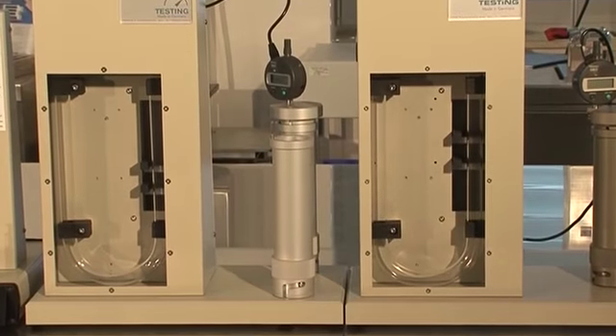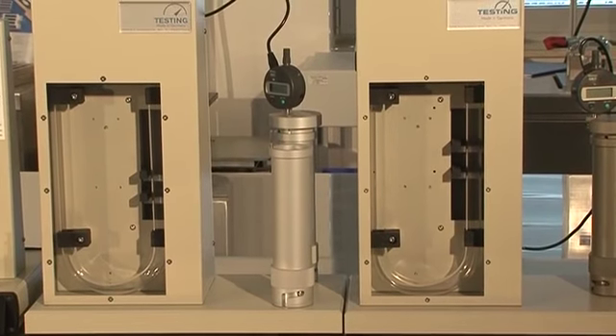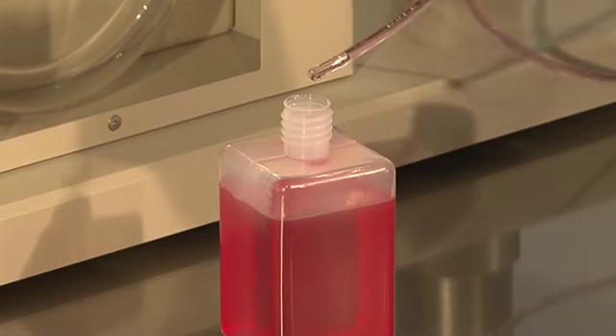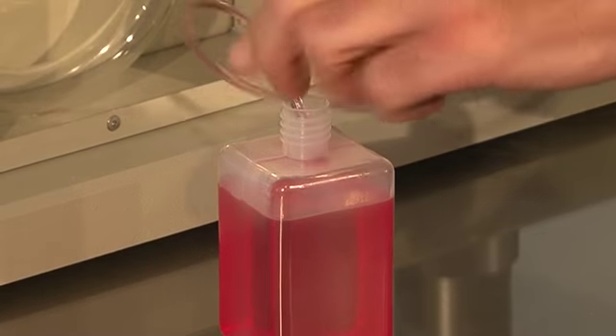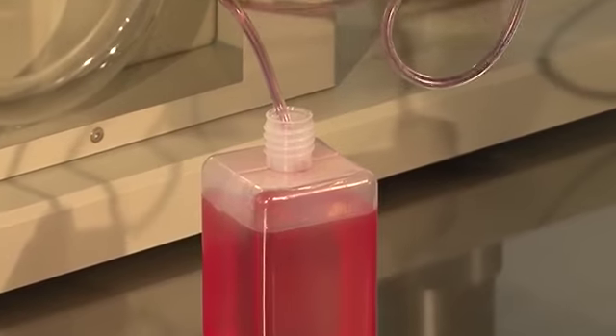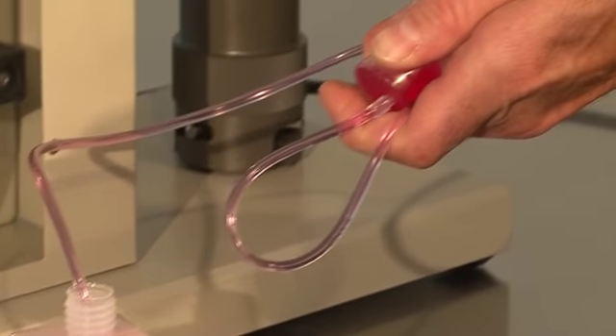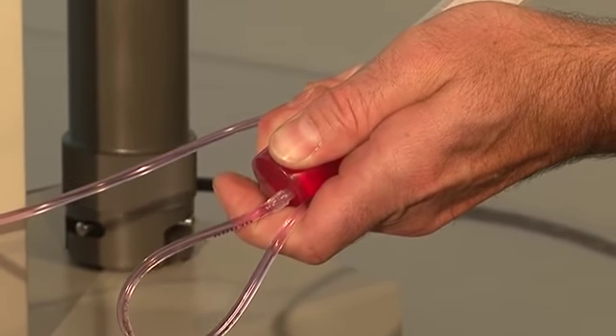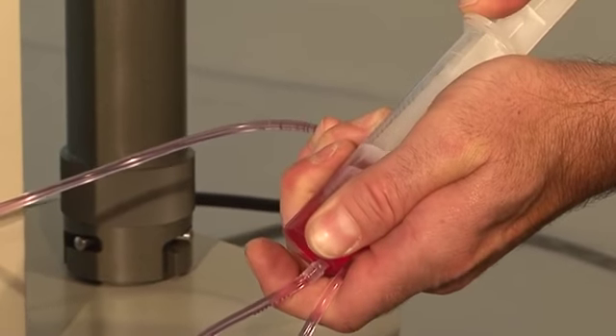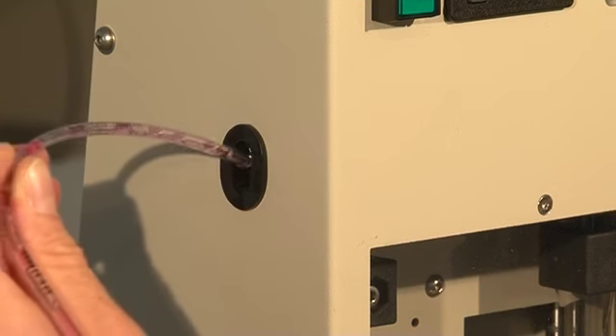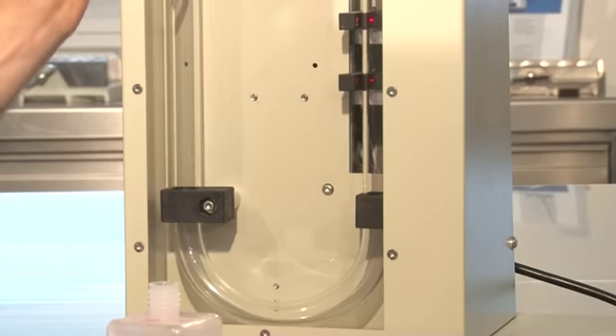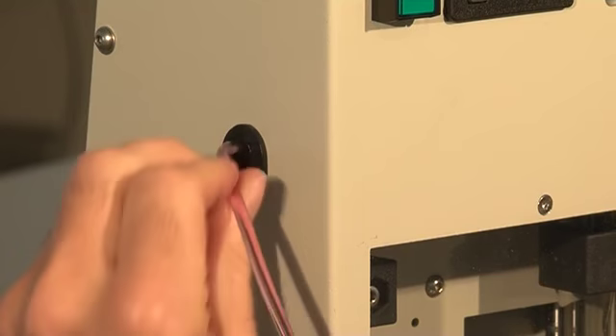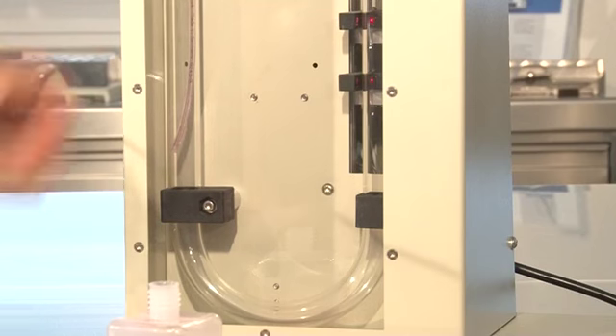Irrespective of the type, the Blaine device must first be set up and aligned on a stable, level and vibration-free surface. With the aid of the filling syringe and tube, the manometer liquid supplied is sucked in from the bottle. Approximately 60 millilitres is required. During the filling process, the end of the tube is inserted into the left side of the metal casing in the U-tube.